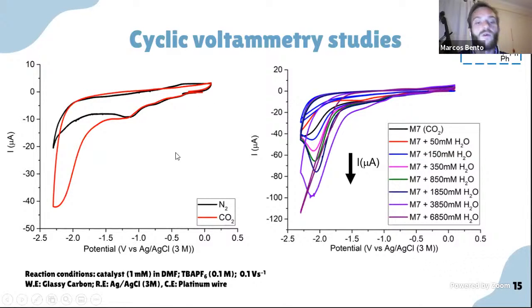So, firstly, we did a cyclic voltammetry study under carbon dioxide, which demonstrates an increase of the current and indicates that this molecule can be a good catalyst for this type of conversion. Through the addition of different water concentrations, we observe also an increase of the current, which can be indicative that water can enhance the conversion of carbon dioxide.